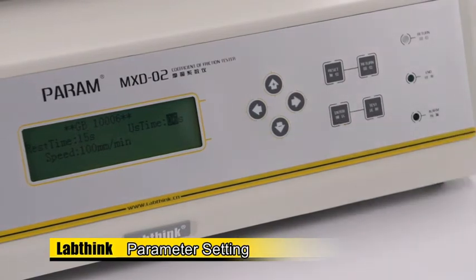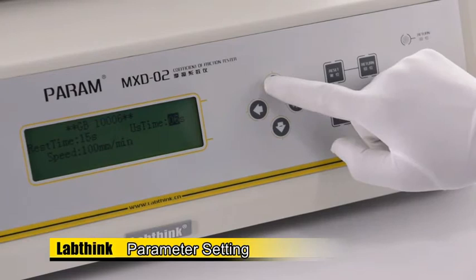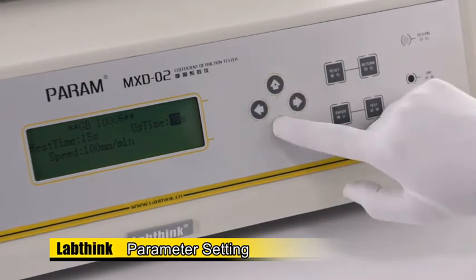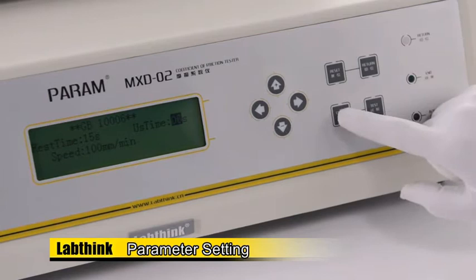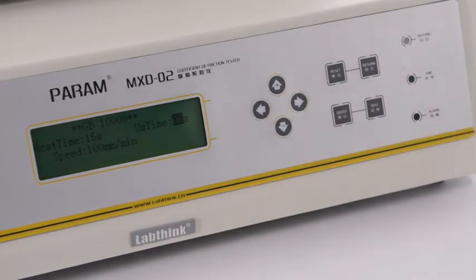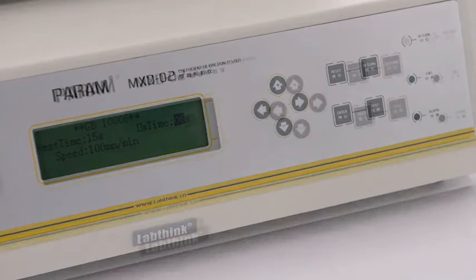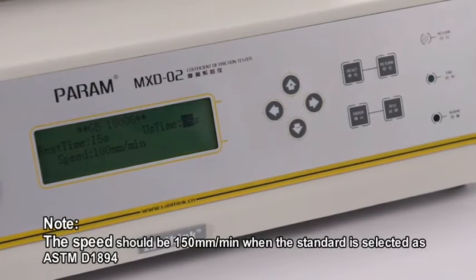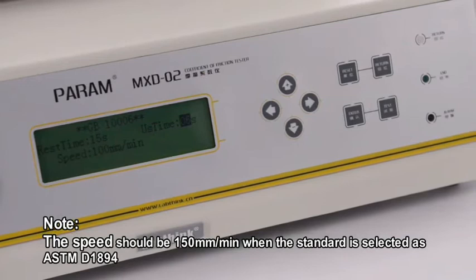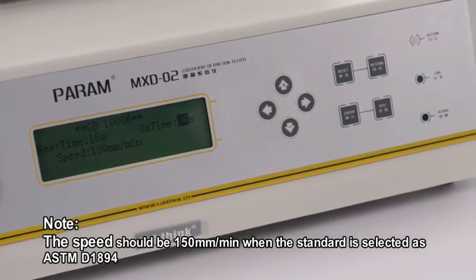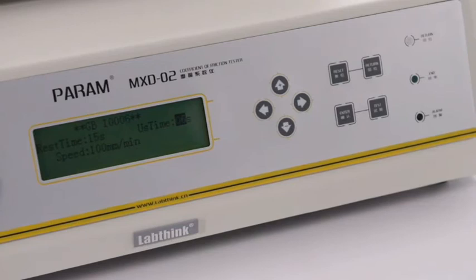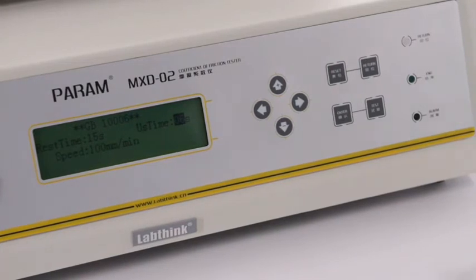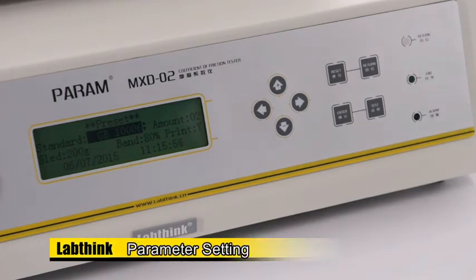The data collected in the first 6 seconds will be used to calculate the static coefficient of friction, and the data collected in the remaining time after 6 seconds will be used to calculate the dynamic coefficient of friction. The speed cannot be changed, which is 100mm per minute, required by GB10006 or ISO8295. Press Return to return to the preset interface. Set amount as required and press Enter to save the setting.